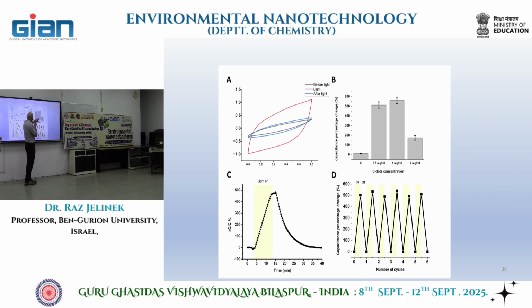Here you see the energy, the capacitance of the capacitor. So just by having carbon dots, we get a very high capacitance. And what you see here is cycling. We can charge and discharge the capacitor many, many times just by shining light. So we shine light, high energy. We charge the capacitor. We turn off the light, low capacity. High, low. This supercapacitor can be used 1,000 times just by shining light.